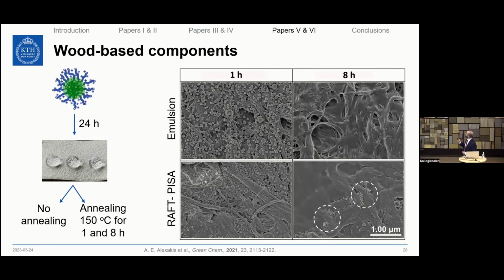However, we also noticed that in the case of PISA nanolatexes, we have these spherical aggregates, even after 8 hours of annealing, which is quite excessive. And we hypothesized that this was a result of the structural stability that was imposed from the higher molecular weight macro-RAFT agent that we used in the case of PISA.